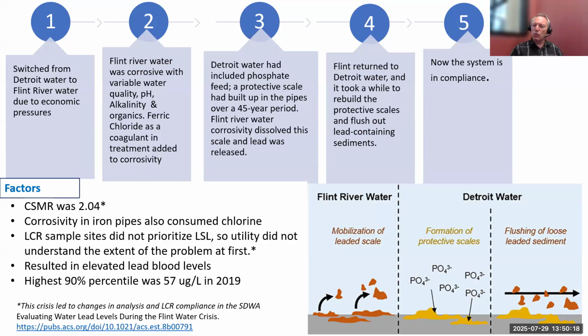and where it says Flint River water, they had the release of the lead scale, the lead containing scale, and then they started feeding the orthophosphate, and they started reforming those scales. And at the same time, they were using flushing to get rid of the lead containing sediment. So it was quite a process. A lot of work went into this to restore the system.